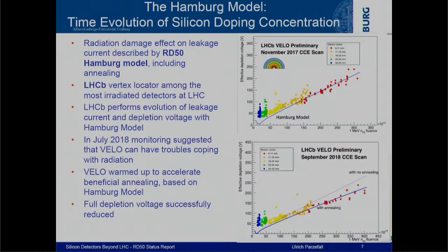Based on this RD50 Hamburg model, the decision was made to warm up the detector in a targeted way to accelerate the beneficial annealing, so they could reduce the effective doping concentration and also the depletion voltage. You see these two lines: this is what you would have had with no annealing. Notice there's more radiation collected now in September 2018, yet you're still comfortable running with this targeted annealing step.